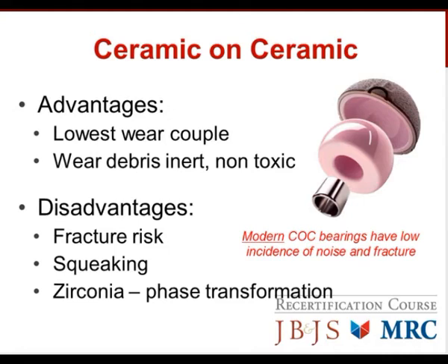Ceramic on ceramic total hips have a number of advantages. This is the lowest wear bearing couple that we have. The wear debris tends to be inert and non-toxic. The disadvantages include fracture risk and squeaking. With modern ceramic on ceramic bearings, there is a very low incidence of noise and fracture, but it does remain a concern. Some of the older zirconia heads had phase transformation concerns that limited their long-term survivorship. Despite these advantages, I think there's limited enthusiasm for ceramic on ceramic in North America, one reason being cost.